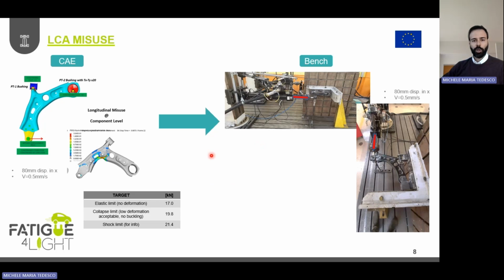So a unique load applied in this direction with the component that is blocked here in the bush and also here. And in this image, you can see the simulation results in terms of deformation of the component. The target that we have to pass is, for the elastic limit, we need to go over 17 kilonewton. For the collapse, the minimum acceptance is 19.9 kilonewton, and for the shock limit is 21.4.